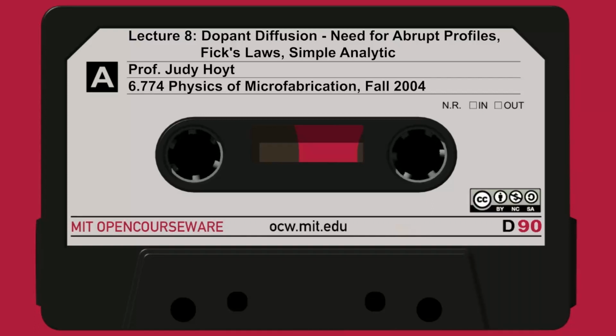So it's a convenient way of calculating resistance of various structures in semiconductor devices. So let's go on to slide number 4. What we just talked about was for a sheet that was uniformly doped to a given dopant concentration. If the doping concentration throughout the sheet is non-uniform in depth, then we can still calculate the sheet resistance, but we need to do an integral. The sheet resistance is just rho over xj, but at this point, we need to integrate.